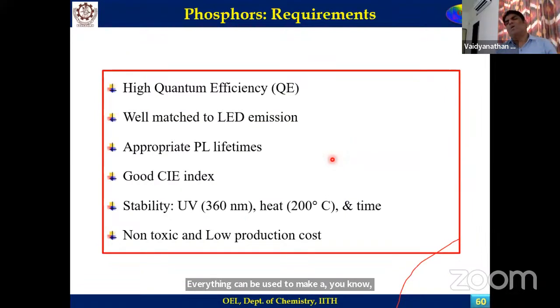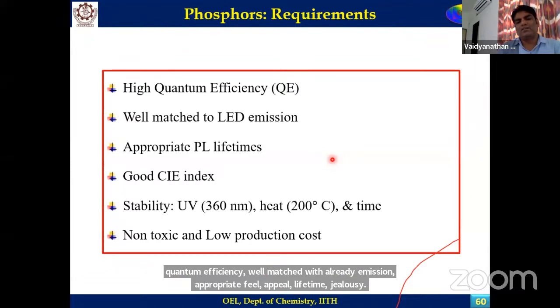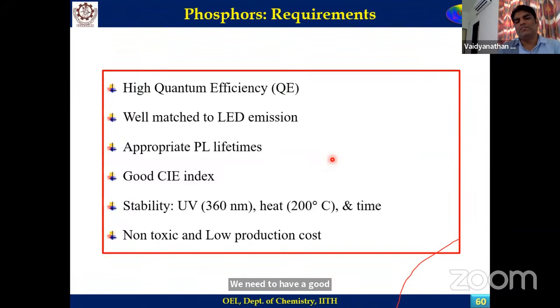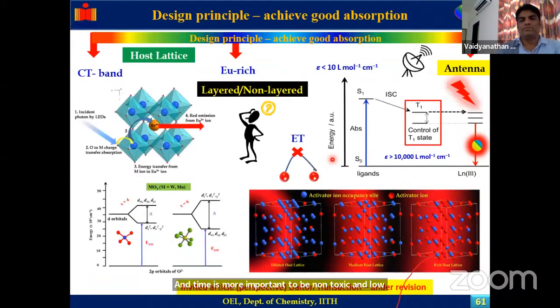What could be the long-term goal? We should have a high quantum efficiency, well matched with the LED emission, and an appropriate PL lifetime. We need to have a good CRI, stability under UV, 360 nanometer, and heat, 200 degrees C, and time is more important. It should be non-toxic, and low production cost should be there. So we made some design principles.